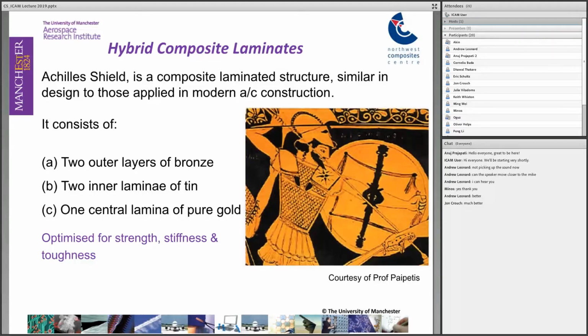But if you look at the construction, it's been optimized for strength and stiffness, while the pure gold, the softer material, provides a bit of toughness. So the spear cannot break the shield in a brittle manner, and at the same time cannot penetrate.